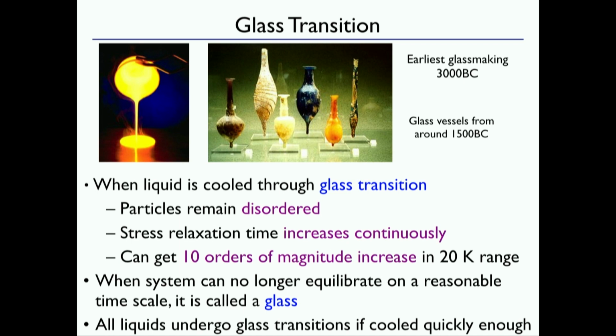And what happens as you go through this glass transition is that the particles remain in a disordered configuration, as in the liquid, and the stress relaxation time increases continuously. So what do I mean by that? I'm going to call that tau alpha, okay? And it's the time for the system to reach equilibrium. It's called stress relaxation because what's the difference between a liquid and a solid, right?